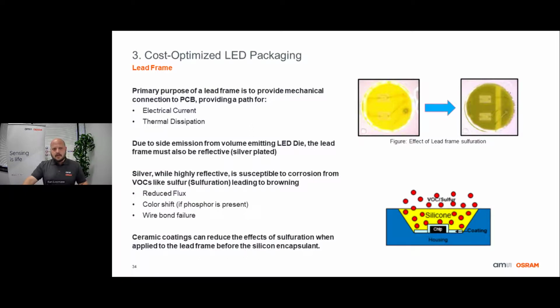When sulfur interacts with silver plating, it goes through a process known as sulfuration. This can leave the lead frame brown and brittle, as we see in the image in the upper right here. This browning can lead to a reduction in flux, as the lead frame is now less reflective. This also can lead to a color shift for phosphor-converted LEDs, as there are now fewer photons being down-converted due to the lower reflectivity. The corroded lead frame is now also more brittle, and this could potentially lead to increased risk of wire bond failures. Now, in order to minimize the impact of sulfuration, a ceramic coating can be applied to the lead frame, as shown in the image in the bottom right. Thicker coatings provide greater protection, but can also reduce the reflectivity.